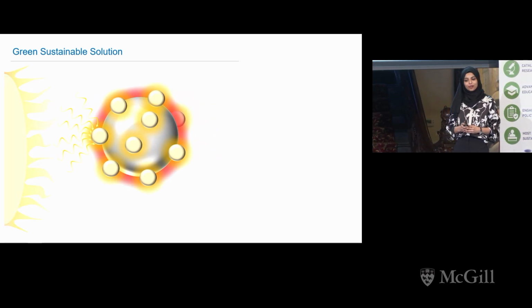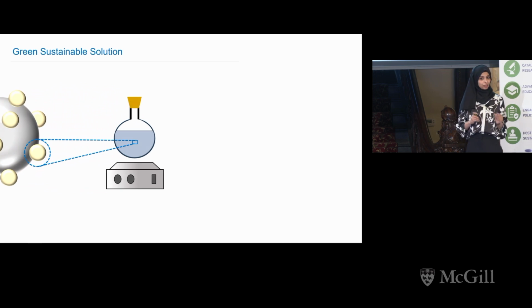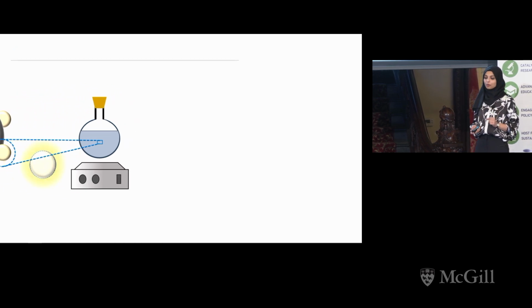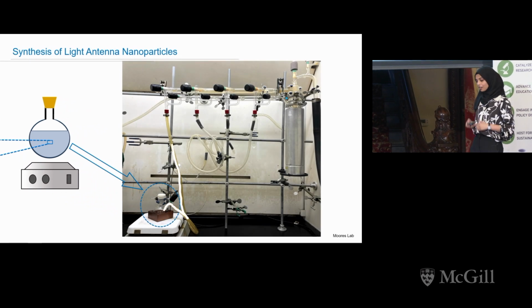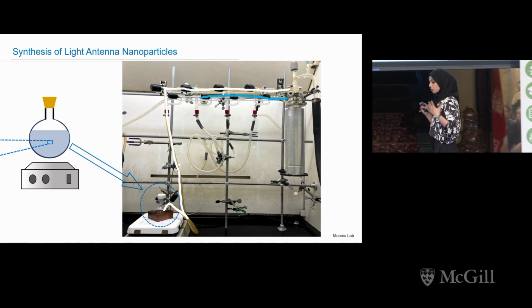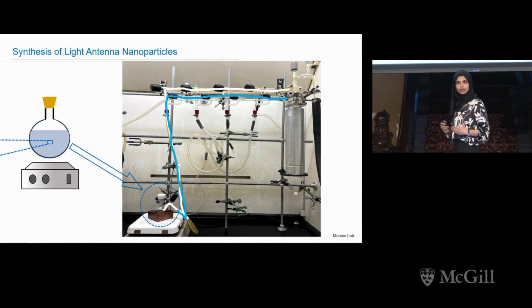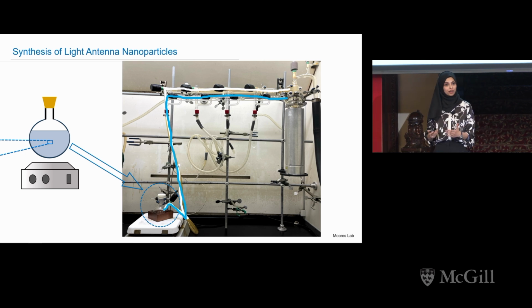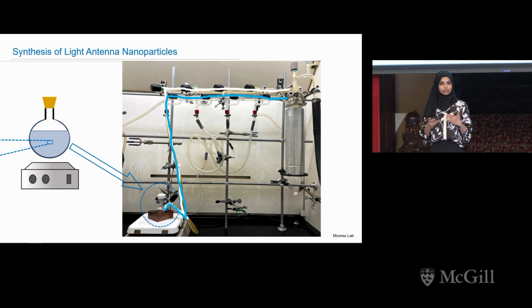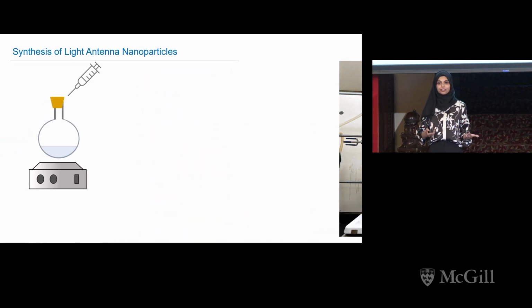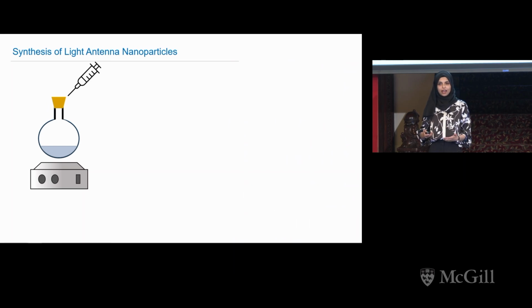The light antenna nanoparticles of my interest are aluminum nanoparticles. These were synthesized using a special fume hood setup called a Schlenk line. In order for the reaction to begin, the reactor was first placed under inert vacuum, followed by an inert environment. Once the reactor was in an inert environment, chemicals were added to start the reaction and eventually wind it up.